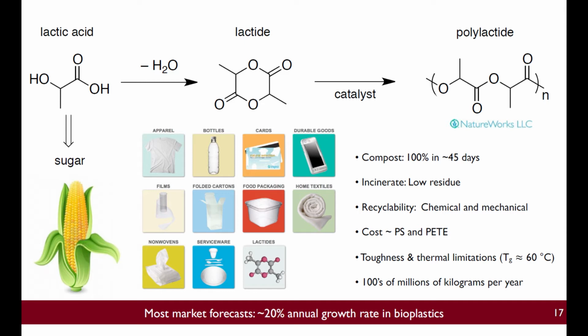What's interesting about this polyester is it's used for so many things, both disposable and durable goods, and it behaves not unlike polystyrene from a materials property standpoint. However, it can be 100% composted in about 45 days. It can be incinerated with low residue. It can be both chemically and mechanically recycled. And its cost is actually comparable to polystyrene and polyethylene terephthalate. It does have some limitations. It's not the toughest polymer you'll find out there. And there are some thermal limitations with respect to its softening point or glass transition temperatures around 60 degrees Celsius.